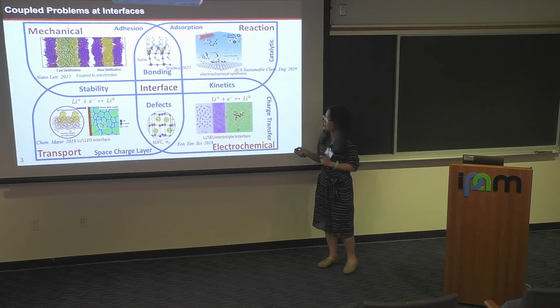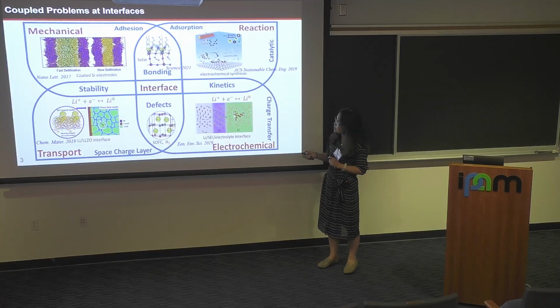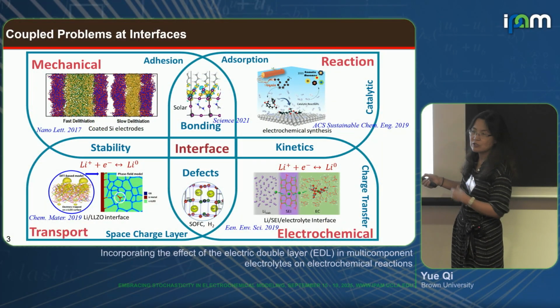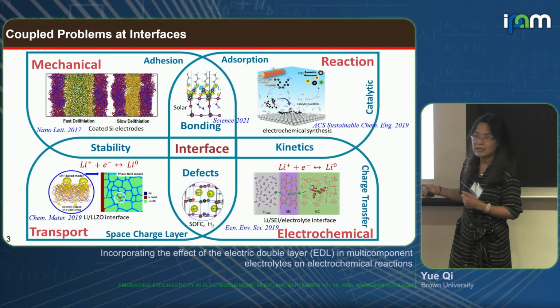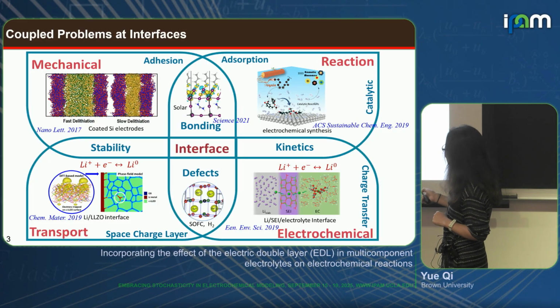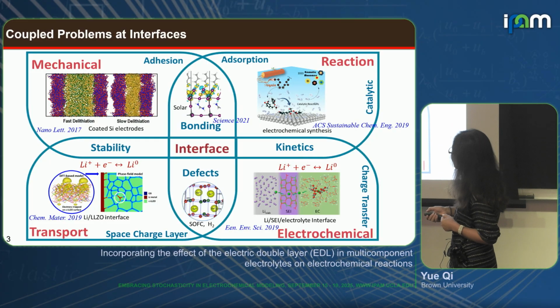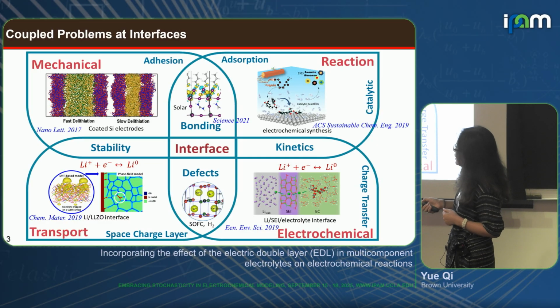Right, so look at this. This is a lithium ion. The lithium ion goes from the solvent across this interface passivation layer and lands on the lithium electrode and meets with the electrons. This is a perfect lithium ion transfer reaction, which won't happen every cycle. However, if the electrons did not stay here but go to the electrolyte, and we have electrolyte decomposition, you heard a bit, that's kind of losing the electrons in our battery.